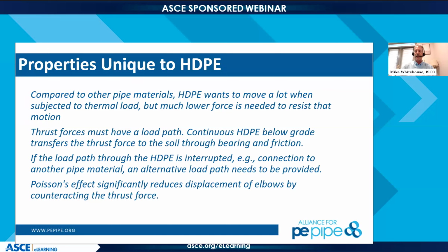Certainly. I appreciate that, Alan. Typically, you do have a long-term and a short-term modulus. And if you have a seasonal change where the environment is primarily responsible for your delta T, or your change in temperature, you typically will use a much lower modulus than if you are in an Arctic condition in the polar region where you have a piping that connects to a tank. And that tank has a float in it that will send process fluid down your line. And that tank is holding at 120 degrees F. And your effluent is coming out very hot while you're in a cold environment.